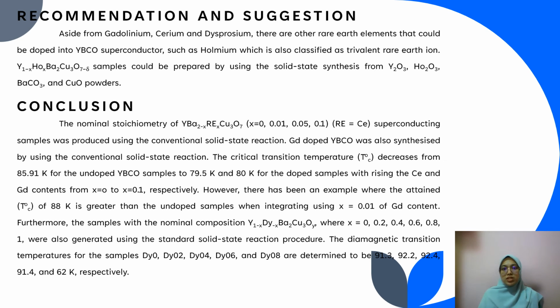However, there has been an example where the attained critical transition temperature of 88 K is greater than the undoped sample when integrating using x equal to 0.01 of Gd content. Furthermore, Dy doped YBCO were also generated using the solid state reaction.